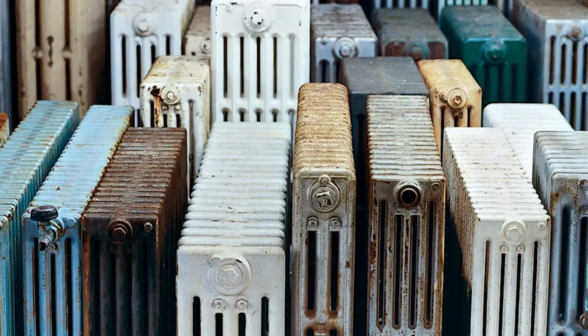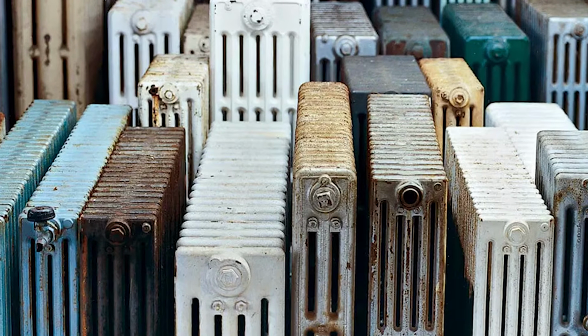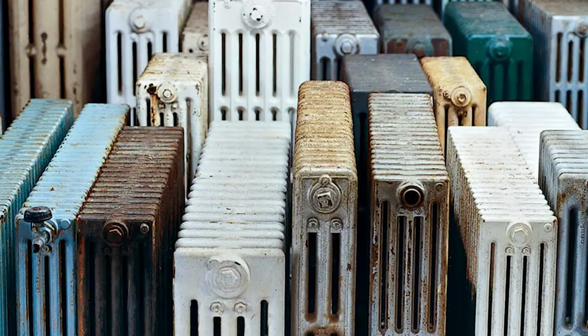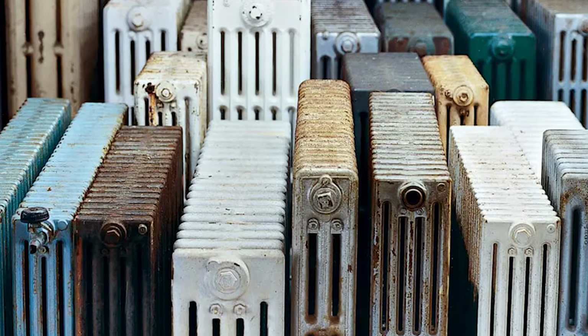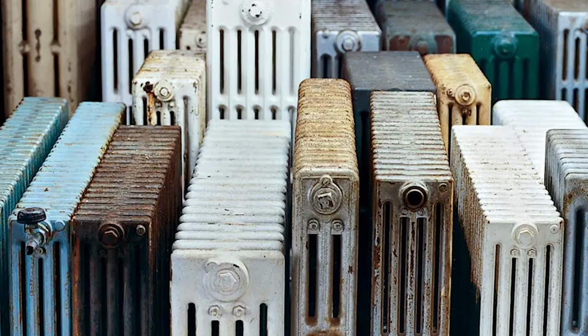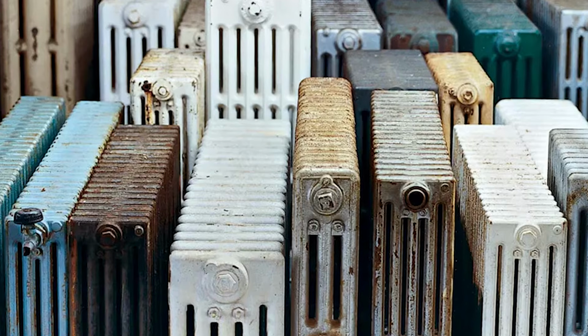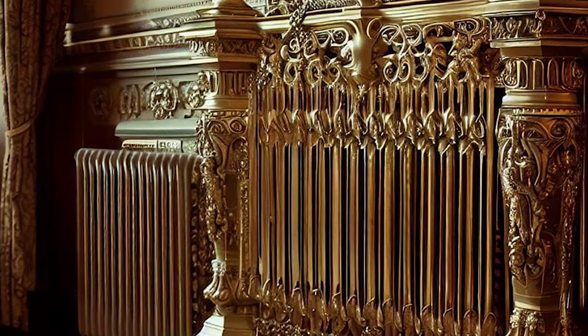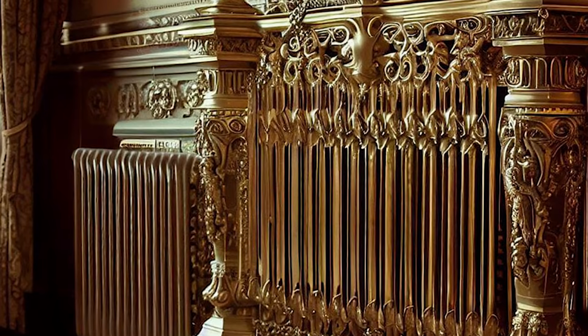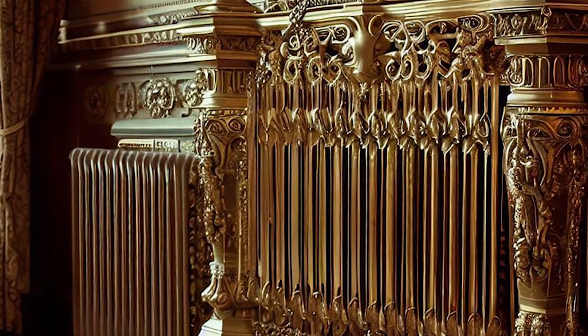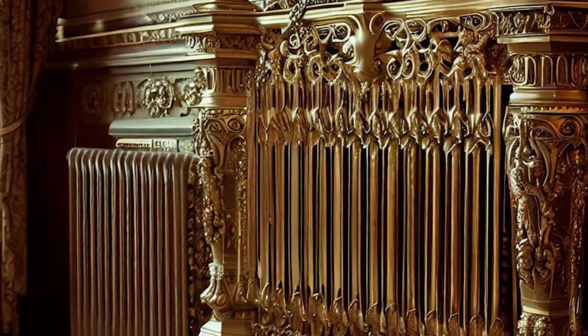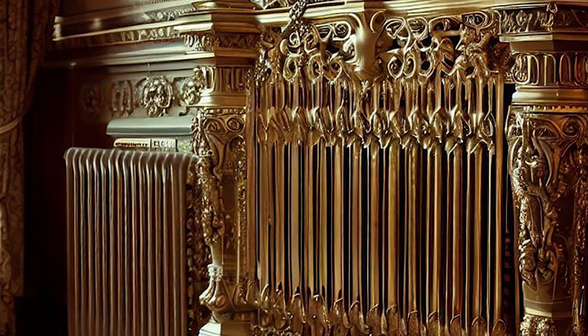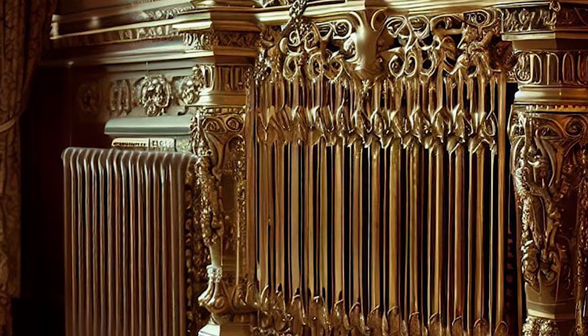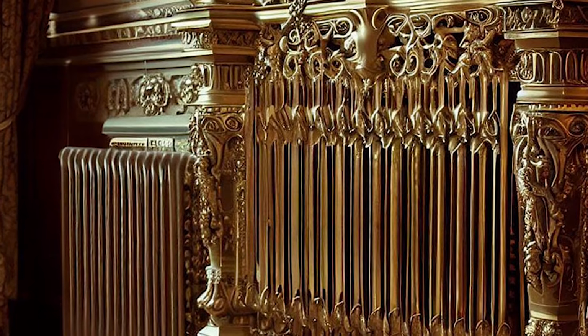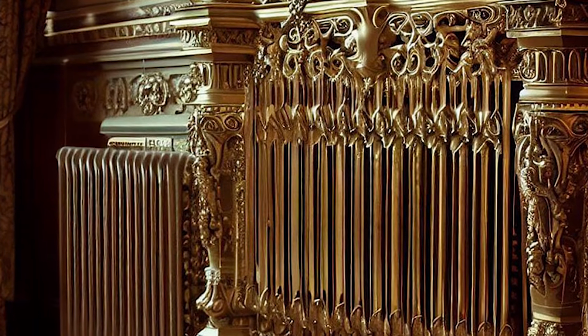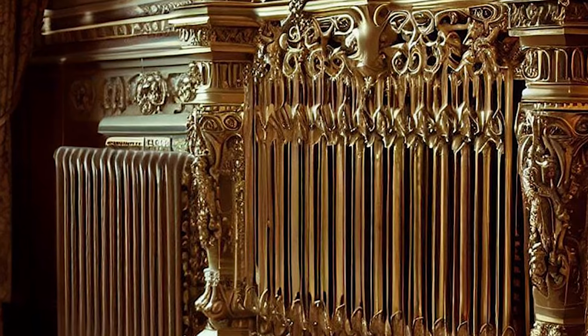By 2015, the first pinhole leaks appeared in radiator sections located in areas where water circulation was poorest and chemistry control most difficult. The leaks started as weeping that stained ceiling tiles and wall surfaces, then progressed to active dripping that required emergency repairs. Chen discovered that individual aluminum panels could not be repaired effectively, requiring complete replacement of failed sections. The modular design that had made installation quick also made partial repairs impossible when corrosion penetrated the thin walls.